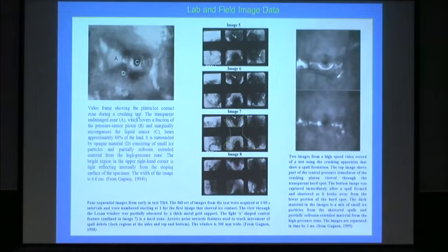So just recapping on some of those experiments, this was the lab test where we had a pressure sensor with a thermocouple and a liquid sensor on it. This is hard zone ice here. You can see through the hard zone ice because it's not damaged, and here's fractured, shattered spall debris around there.